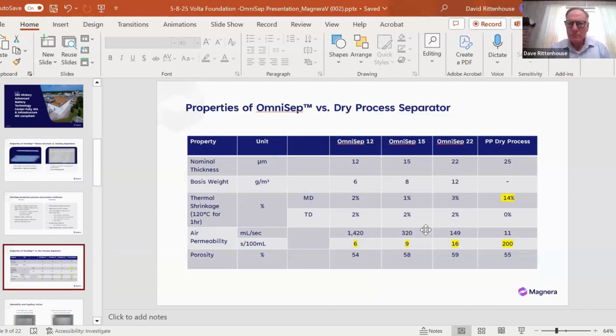So to look at some of the key properties, on the right-hand side, you can see this compares our OmniSep 12 micron, 15 micron, and 22 micron at 120 degrees C. This is published data for the stretch film separator. You see the degree of shrinkage, 14%. The air permeability is very interesting. The industry reports using units of seconds per 100 milliliters. This is the Gurley number. Celgard is 200. You can see how much more open our material is to airflow.